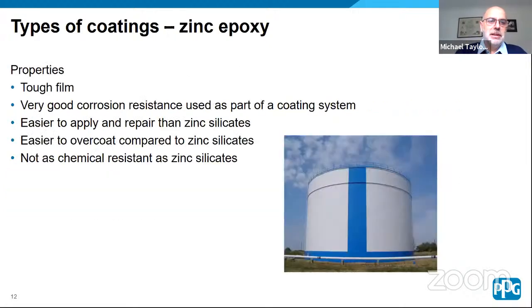In terms of properties of the zinc epoxy, again, a tough film. You can have slip resistance certification with these, but usually the zinc silicates are used. Good corrosion resistance when they're used as part of a coating system. They are easier to apply and repair than zinc silicates, but they're not as chemical resistant. When you're coating with zinc coating, it's also important to note that if you leave a time between the zinc coating being applied and the intermediate or top coat being applied, they can be subject to contamination with zinc salts, and it's important that these are removed before you overcoat them. Zinc epoxies can also be used to spot repair galvanized steel if that's broken down, for example.